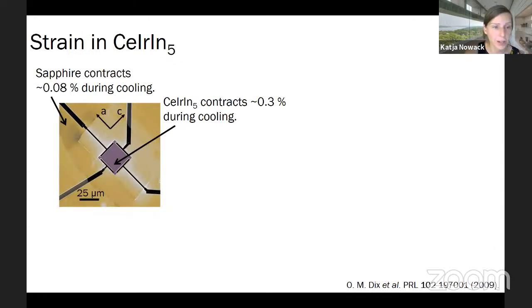It turns out, if you think about it, these microstructures actually have a strain field built into them. This is because the CeIrIn5 is glued with a thin layer onto sapphire. Sapphire thermally contracts during cooling, but not that much, about this amount. Whereas CeIrIn5, being a metal, contracts a more substantial amount, about 0.3%. And so there's differential thermal contraction between the substrate and the actual device.